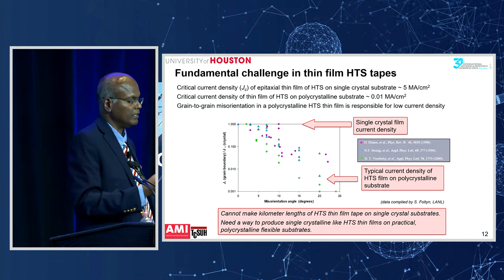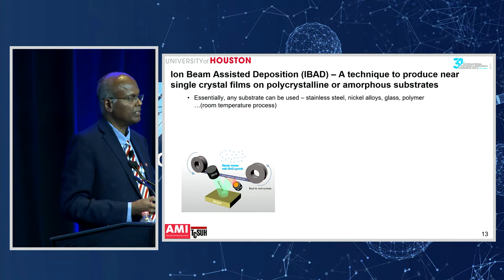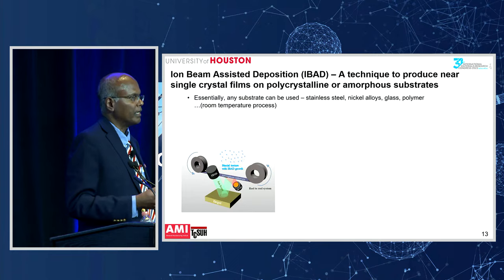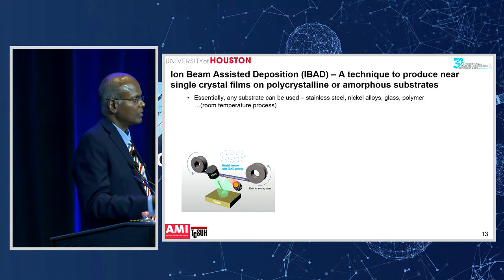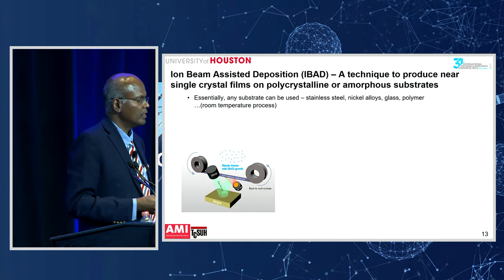The solution that was developed several years ago is a technology called ion beam assisted deposition, or IBAD. This is a very, very versatile process. You can use any substrate. You can use a nickel alloy like we do. We can use stainless steel. We can use glass. You can even use polymers for that matter. So what you do is deposit a film like magnesium oxide in a roll-to-roll process.